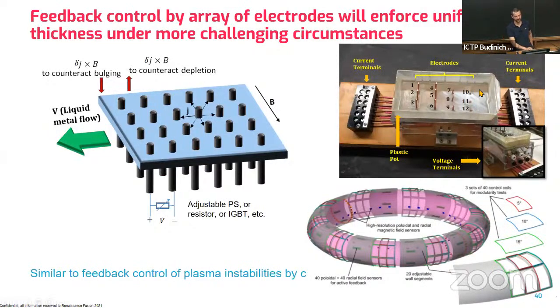instabilities, we have a simple solution, which is an array of electrodes immersed in the liquid metal, by which, simply by controlling the potential of these different electrodes, we can design the current pattern in the liquid metal such that in regions where the liquid metal is bulging, we apply a slightly stronger J cross B. In regions where it is depleting, a slightly weaker J cross B.